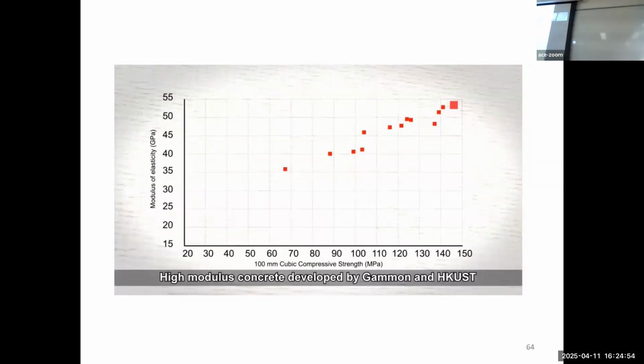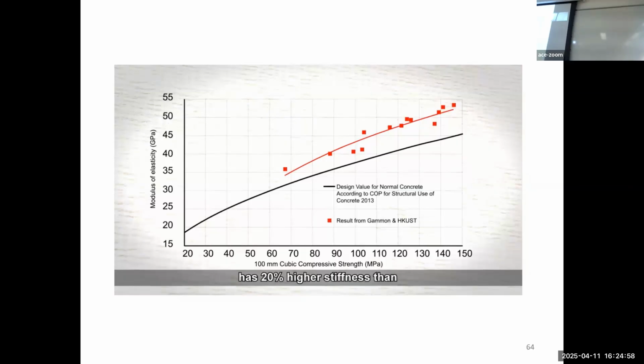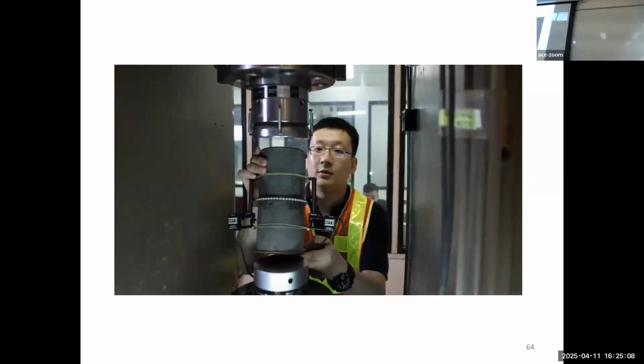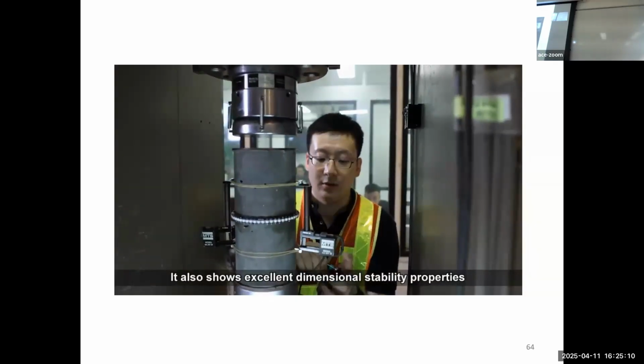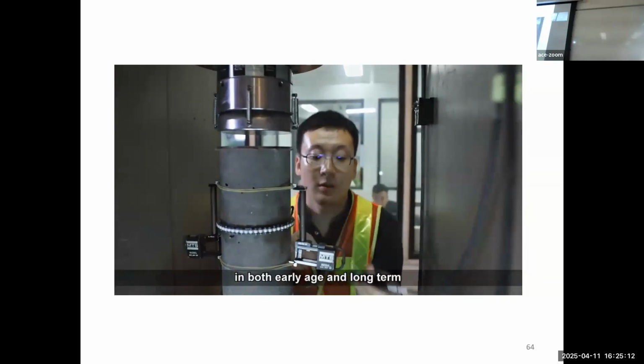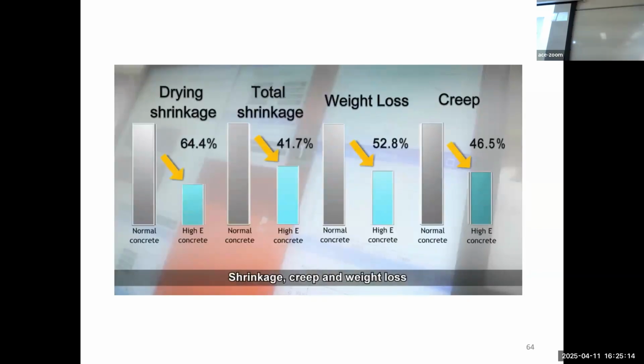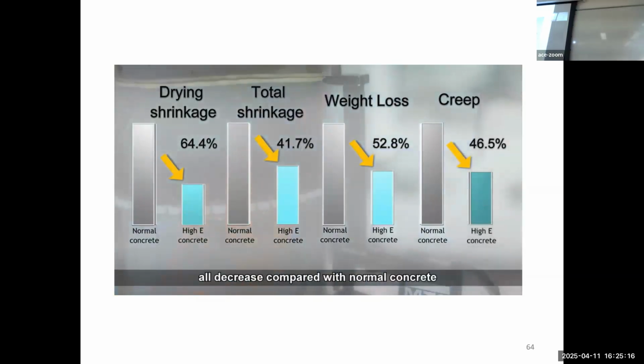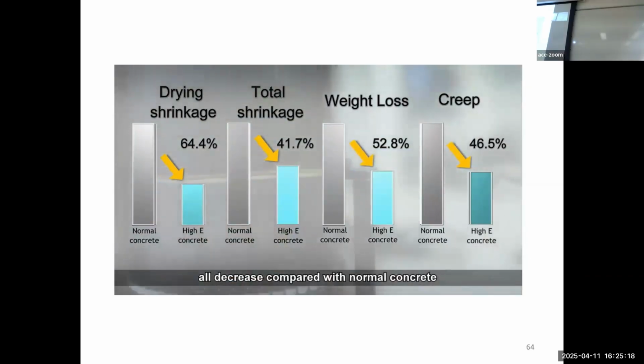High modulus concrete, developed by Gammon and HKUST, has 20% higher stiffness than normal concrete in the Code of Practice. Therefore, up to 20% materials can be saved to maintain the original structural stiffness. It also shows excellent dimensional stability properties in both early age and long term. Shrinkage, creep, and weight loss all decrease compared with normal concrete.